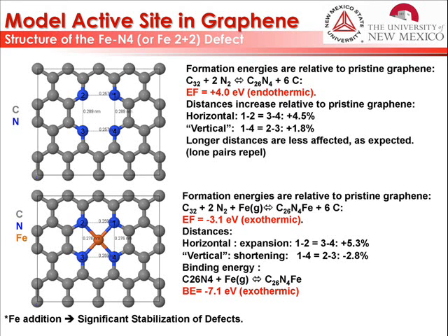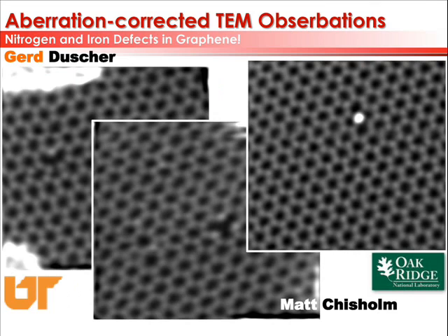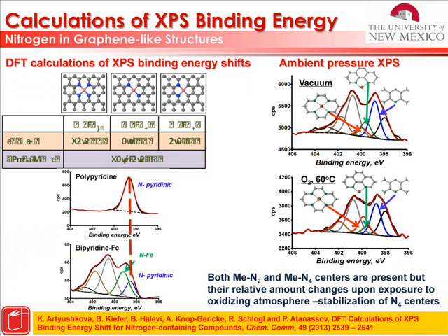Again, I apologize for this low resolution. But look at this. This is a TEM image of a single foil of graphene obtained at Oak Ridge National Laboratory with the help of University of Tennessee. These are the 3 nitrogens. There is EELS data that support that. And this is how, when there are only 2 nitrogens, only 1 nitrogen, the site is deformed. When you put 4 nitrogens, this site becomes symmetric, relaxes back again to the normal structure of the graphene.